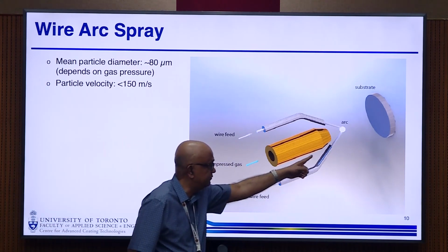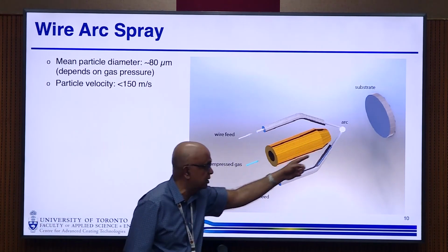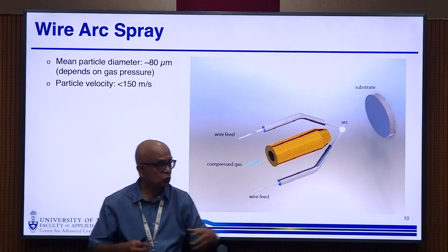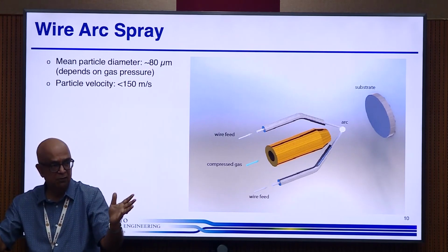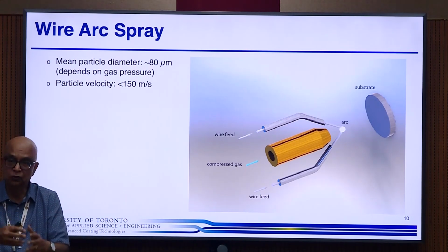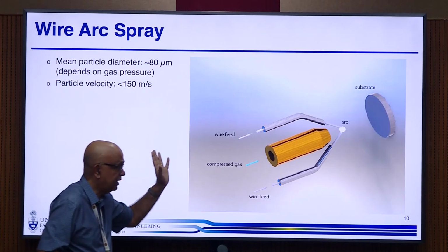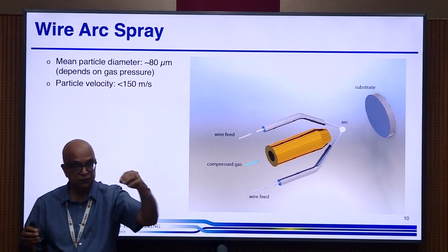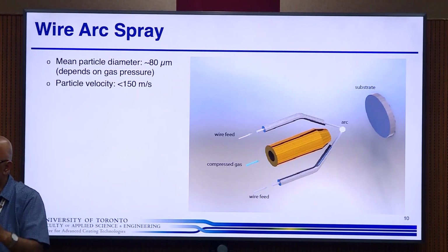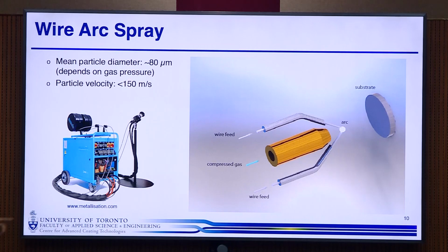You actually have two wires being fed in, you're striking an electrical arc between them, and you're blowing compressed air. So you can generate a spray, and you can do this with any metal. If you can buy metal in wire form, you can generate a spray. The spray then goes out, and the droplets freeze on the surface, and they form a really dense coating. Now, the equipment is very simple. If you are familiar with wire arc welding machines, it's basically the same equipment over here. And so you can buy something like this for about $25,000, $30,000, and you are in business.